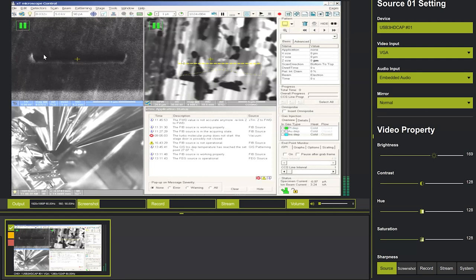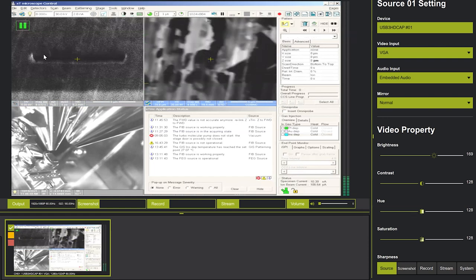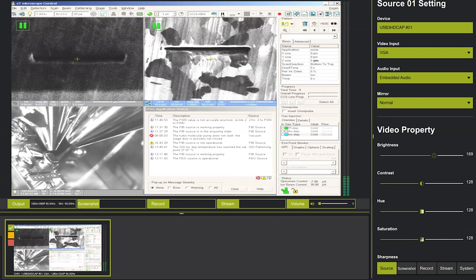The message here is you can create a cross-sectional wall to look at. This is not the hole, but what we are interested in is the cross-sectional wall. You're trying to get a cross-section of it, right? Yes, so ideally I can see a nice view there. This is the cross-sectional wall area, and I removed the material here. But since I didn't remove enough in the Y direction, it's very shallow when you look at it. If I remove more, you can see deeper.